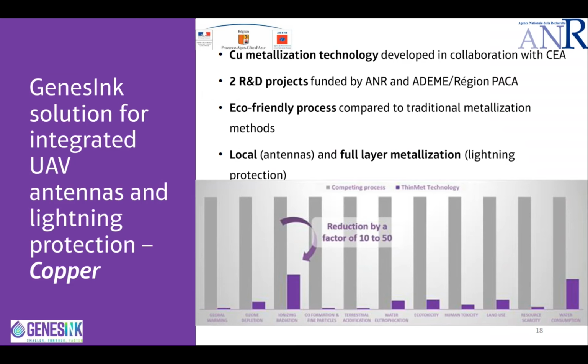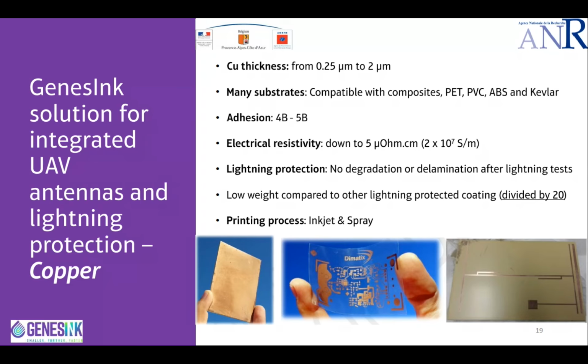We can tailor the thickness of the copper layer from 0.25 to 2 micron, while we keep the electrical resistivity down to 5 micro-ohm centimeter and the adhesion up to 5B. Full metallized surface demonstrators have been realized and tested for lightning protection by our industrial partner in aeronautics, showing very good performance against lightning without any degradation or delamination observed. One of the big advantages of this technology is the reduction of the copper coating weight by a factor of 20 compared to the other lightning protection coatings, meaning that with this technology, we were able to reduce considerably the weight of the coating for the lightning protection.